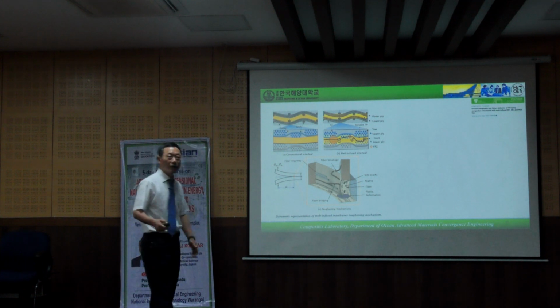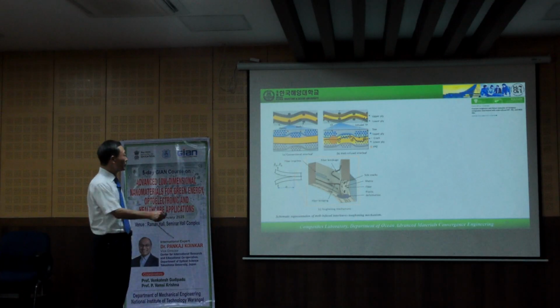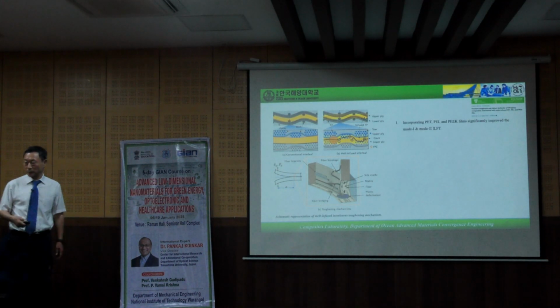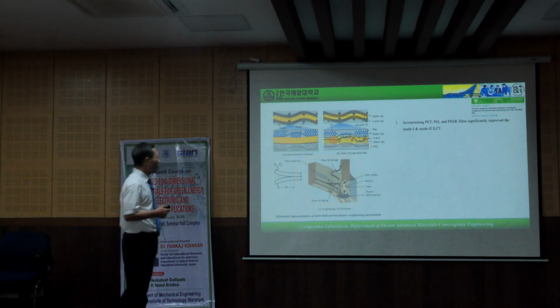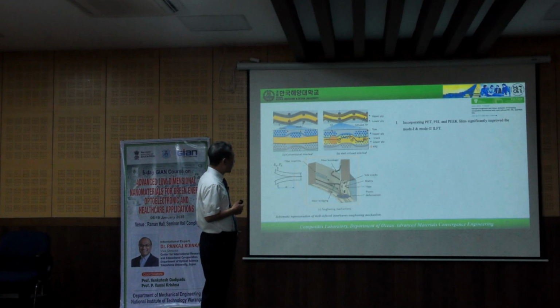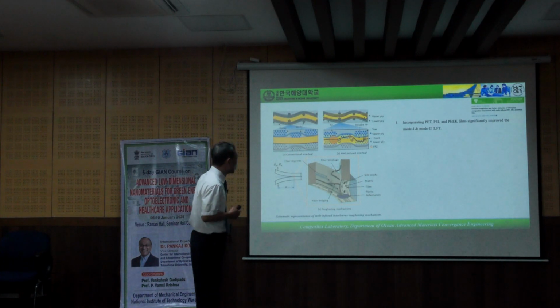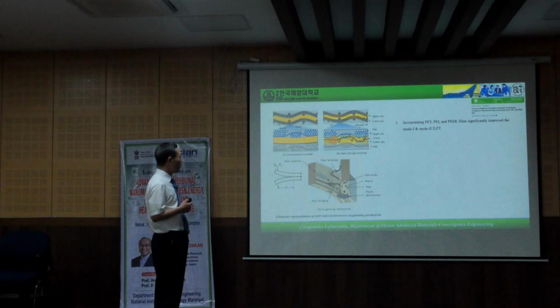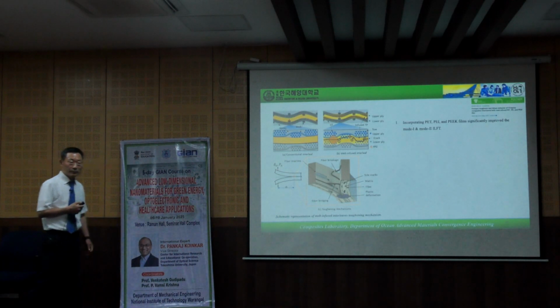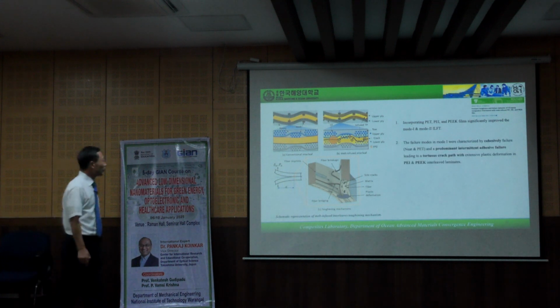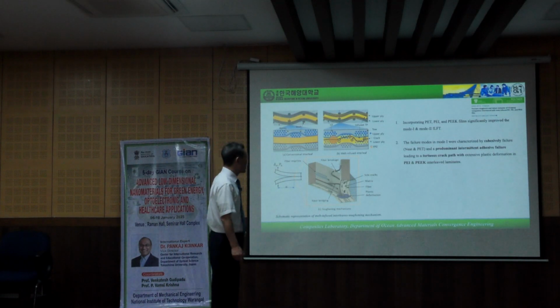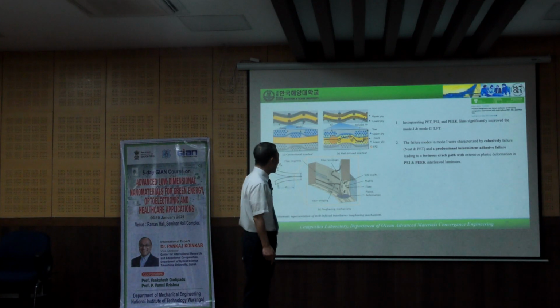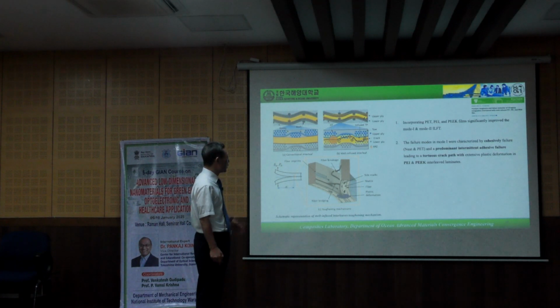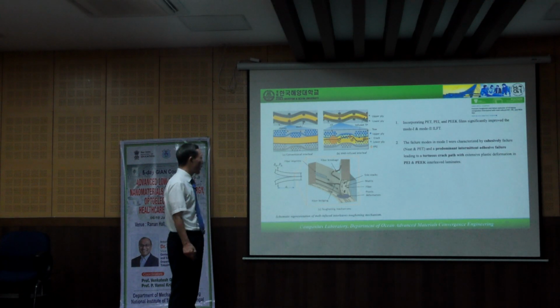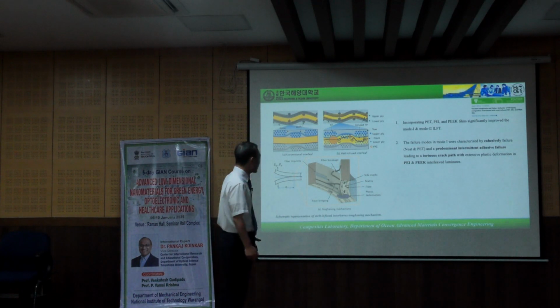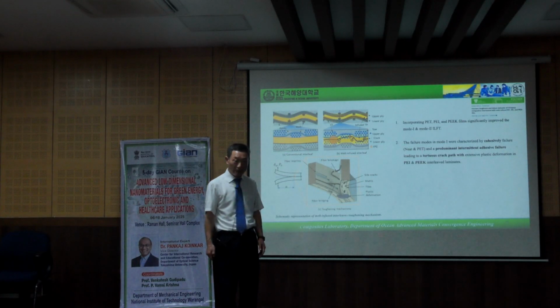This result is published in Polymer Composites. Incorporating PET, PEI, and PEEK film significantly improved the mode 1 and the mode 2 interlaminar fracture toughness. And the failure modes in mode 1 were characterized by cohesive failure and predominant intermittent adhesive failure, leading to the tortuous crack path, with extensive plastic deformation in PEI and PEEK interleaved laminate.